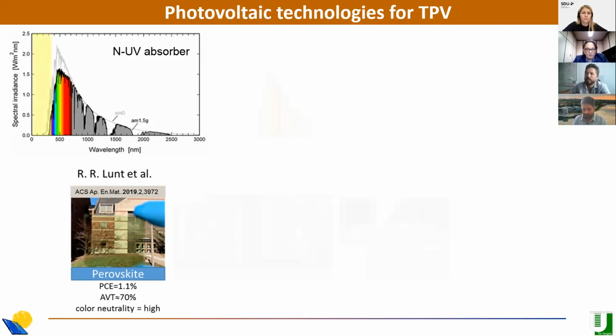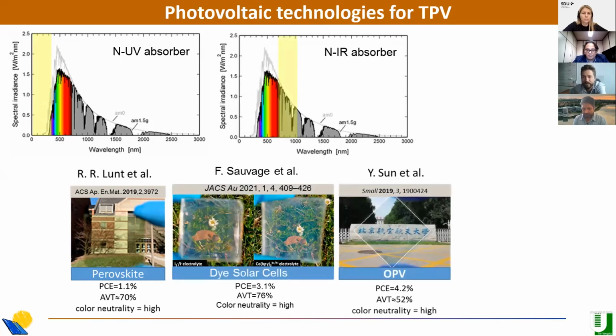Of course, you can do the opposite. You can use a near infrared absorber, and with it you can harvest energy in the infrared part, and there are several technologies that could do this. Of course, it's quite selective. Conventional semiconductors will absorb from infrared down to visible and UV. You need molecules, more or less, to have a selective absorption in the infrared only. And for this reason, the two main technologies are dye solar cells and OPV, organic photovoltaics, both small molecules and polymers.